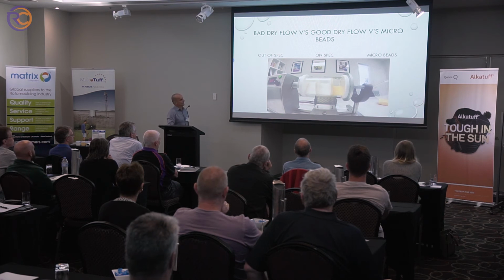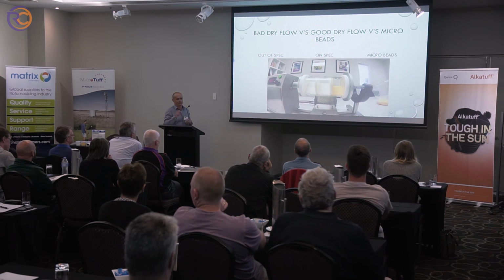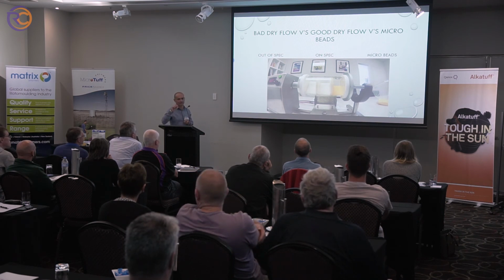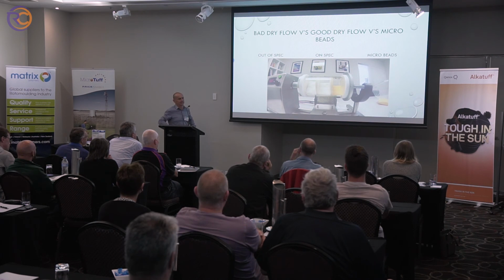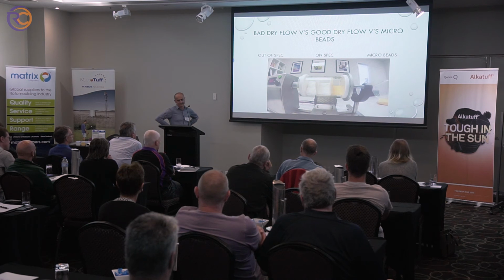That's good and bad. Micro pellets, as I mentioned before, with the powder you have a distribution of particle shape and size. Micro pellets are generally all one shape, so surface finish with micro pellets might not be as good, and the dry flow properties of micro pellets are more like 10 or 15 seconds compared to 27 or 25. So they're going to flow around the mould a hell of a lot quicker than powder, and so if you're going to use micro pellets, you need to alter your moulding cycles.